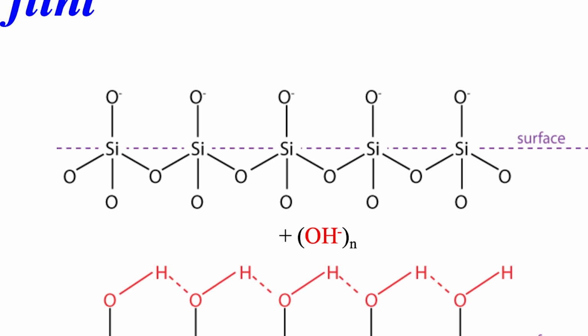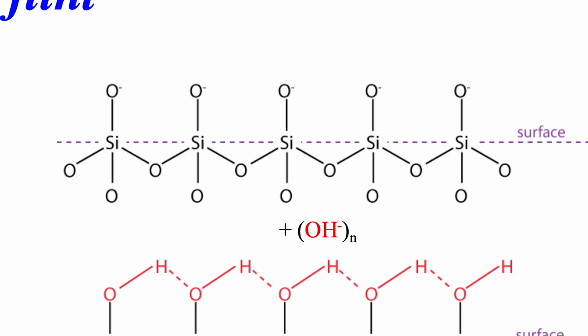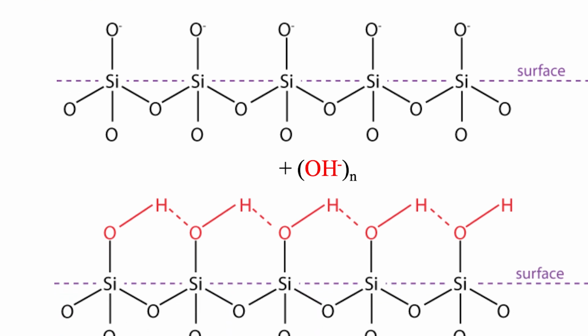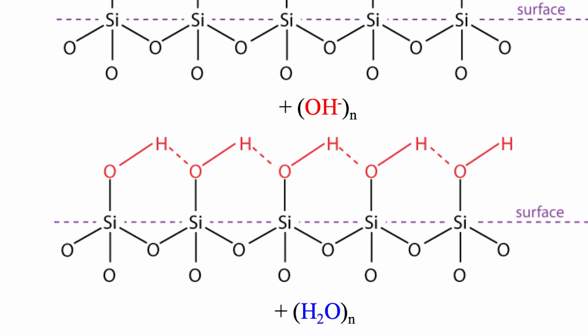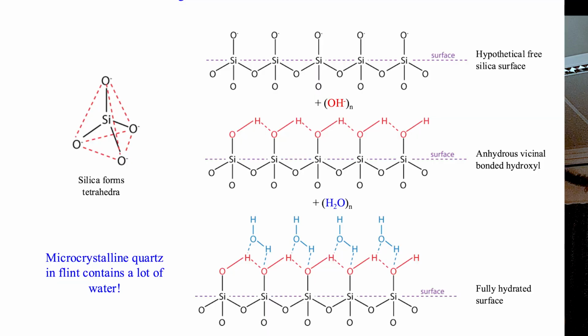this is proving annoying. Little OH hydroxyl groups stick onto this oxygen and then cross-link between them. So we finish up with what's called an anhydrous vicinal bond in there. What can then happen is we get additional water hydrogen bonding onto the silica, onto the hydroxyl groups of the silica itself, and this gives us a fully hydrated surface. If you heat the flint up, we lose some of this water, and eventually we lose these OH groups, and these bonds join in what's called a siloxane bond. So that's where the water occurs, as molecular water and as hydroxyl groups on the surface.